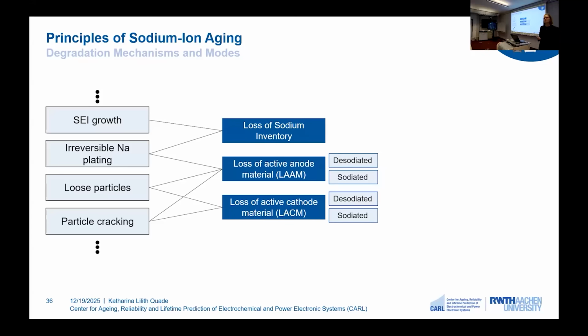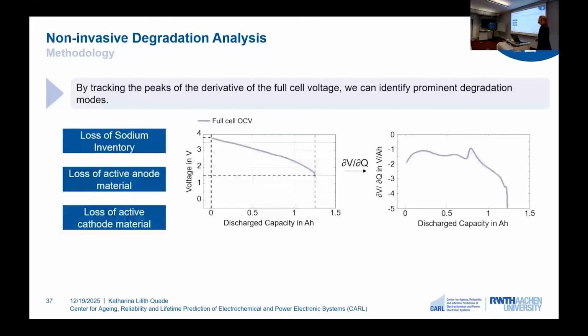And to do this, we leverage a method that is commonly employed for lithium-ion batteries called differential voltage analysis. And here you can see the principle. We can see here the full cell voltage recorded during the reference performance test of our cell. And here you can see the first derivative of the full cell voltage. And we can also see that the first derivative enhances the features from the open circuit voltage. And we can see some bumps and also some peaks here. We now want to assign these peaks to the specific electrodes.